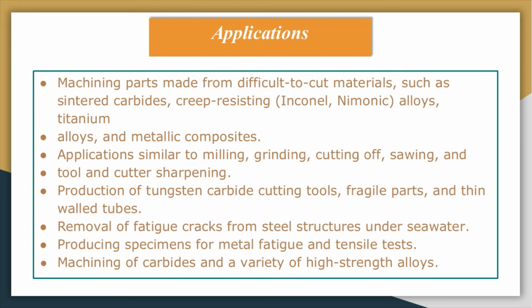Removal of fatigue cracks from steel structures under seawater. In such applications, holes about 25 mm in diameter in steel 12 to 25 mm thick have been produced by electrochemical grinding at the end of the fatigue cracks to stop further development of the crack and to enable the removal of specimens for metallurgical inspection. Then again, it is used for producing specimens for metal fatigue and tensile tests. For machining of carbide and a variety of high strength alloys, we can prefer the electrochemical grinding process. The process is not adapted to cavity sinking and therefore is unsuitable for the die making industry. So these are the applications of electrochemical grinding.